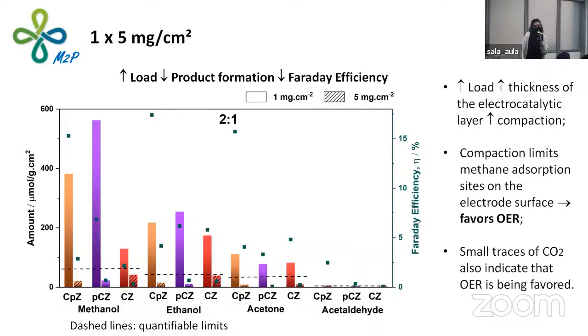And the Faraday efficiency as well was really lower for the 5 milligram per centimeter squared load. And we can assume that there is a relation between the load and the thickness of the electrocatalytic layer that leads to a higher compaction of the electrocatalyst. And this compaction ends up limiting methane absorption sites on the electrode surface, and that probably makes the oxygen evolution reaction more favorable. The small traces of CO2 that were found for both 1 and 5 milligram per centimeter squared loads also indicate that it is the oxygen evolution reaction that is being favored.